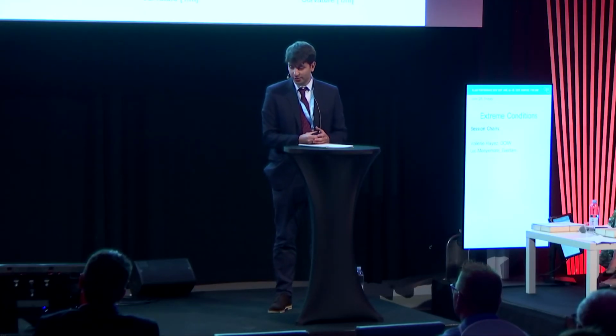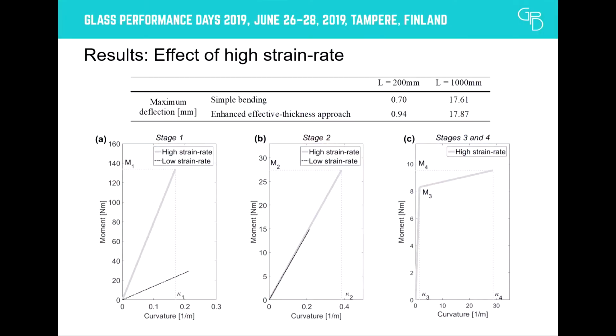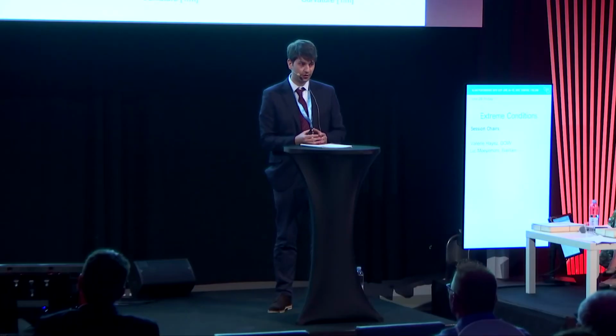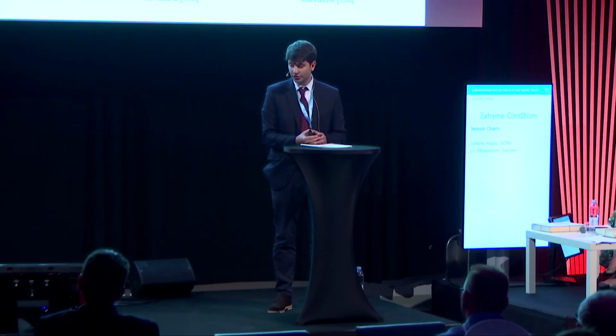Finally, in the post-fracture response, stages 3 and 4, we have plotted the moment capacities, and we've only plotted the moment capacities for higher strain rates, ignoring the moment capacities for low strain rates. This is, as we have discovered in many publications that have done tests under low strain rates for laminated glass beams and have found that there is no post-fracture capacity.